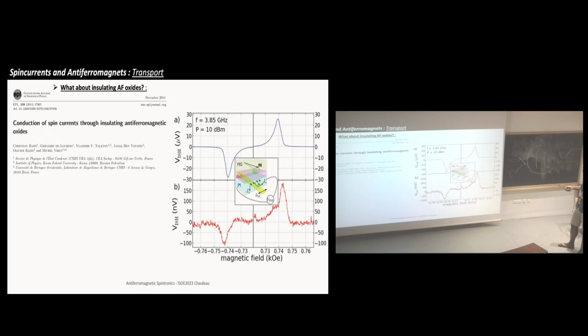And what people have done, they have driven the ferromagnetic resonance. And as you know now from the spintronic lecture, if you drive the ferromagnetic resonance, then you will emit a spin current. Then they are comparing if you don't have NiO and if you have NiO. The first striking thing is that they can see a signal at the platinum if there is NiO. So this is a direct proof that something is going through the antiferromagnetic layer. It's small, but it's there.